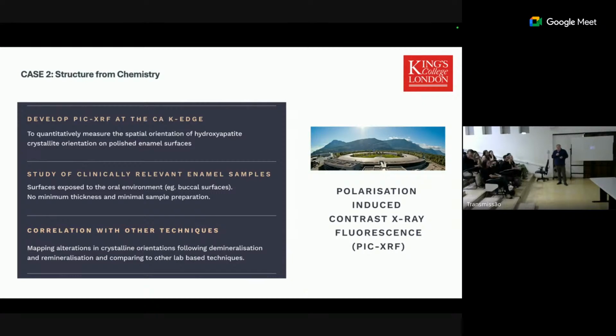However, I wanted to do this with no sample preparation whatsoever. So we looked to a technique that's used in geology at synchrotrons. We didn't invent this technique, we just decided to apply it to a different area. One of the key things about the light produced at these types of sources is that not only is it very, very bright, but we can control something called its polarization. So if you remember that light is both a wave and a particle, the orientation of that wave gives us its polarization.